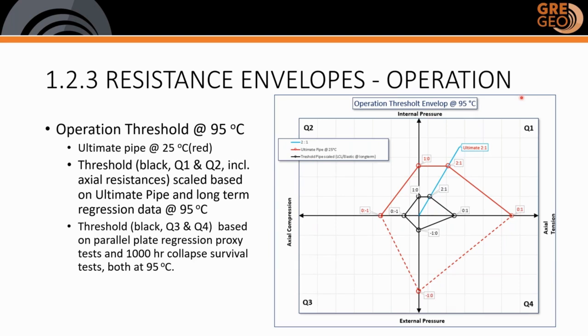For the resistance envelope during operation, we followed the same procedure as for the installation envelope, with the exception of the -1.0 point you see over here, which is based on a 1,000-hour survival test, of which the regression coefficient is estimated from a parallel plate regression proxy test. The samples are taken from the 100-hour survival test discussed before, so that we cover the historical loads the pipes have seen during the installation as well. The parallel plate test can also be used to estimate both temperature and time effects on short and medium term loading.